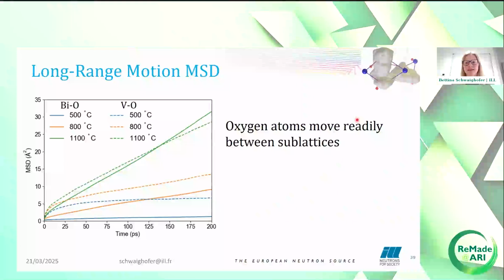To analyze this in a bit more detail, again, we separated the oxygen atoms originating in the bismuth oxygen sublattice and in the dopant sublattice. For BVO, at 500 degrees Celsius, the oxygen atoms from the vanadium oxygen sublattice reach a plateau at about 5 angstrom squared, which is the rotational distance around the vanadium center. As you increase the temperature, the slopes become more comparable, which can be explained by there being more hops between the two sublattices, making the distinction between the two sublattices less meaningful.